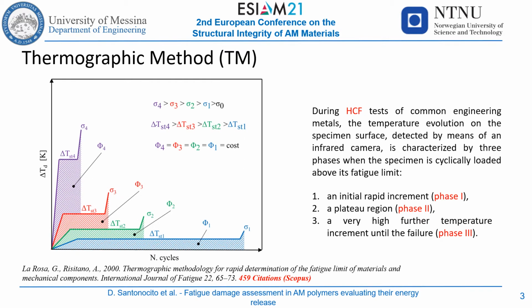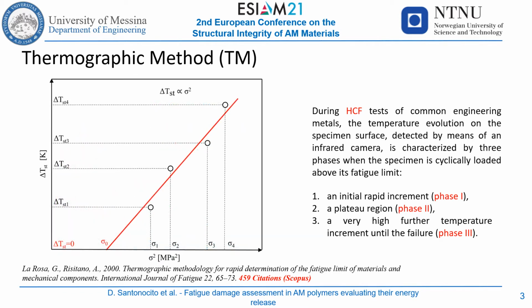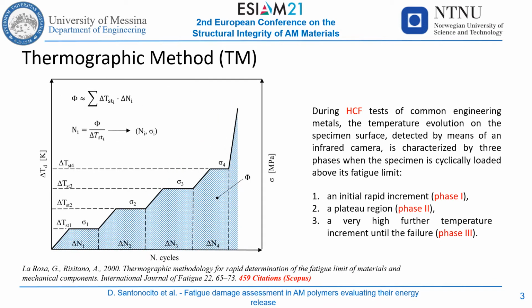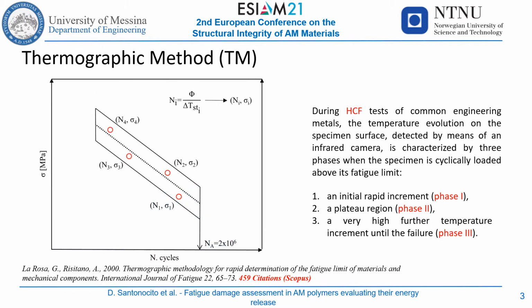Generally, the higher the applied stress, the higher the stabilization temperature, but on the other hand, the subtended area of the temperature-number of cycles curve could be assumed constant and related to an energy parameter phi. If we report the stabilization temperature versus the applied stress, the fatigue limit of the material could be defined as the intersection with the stress axis. In addition, if we stress in a stepped way the material and we evaluate the energy parameter and their different stabilization temperature, it is possible to obtain the number of cycles at which the material will be broken if we cyclically test with that stress, hence obtaining the SN curve.